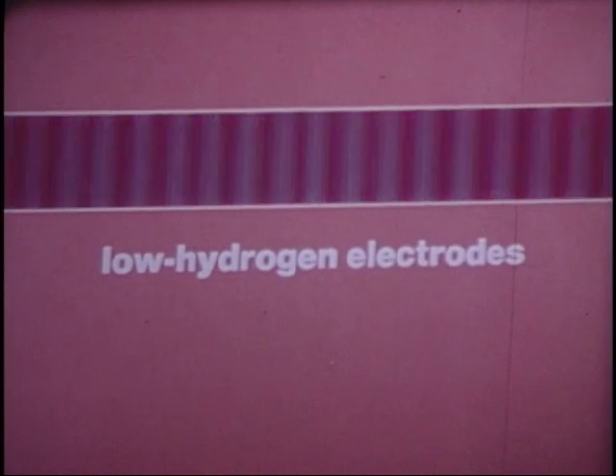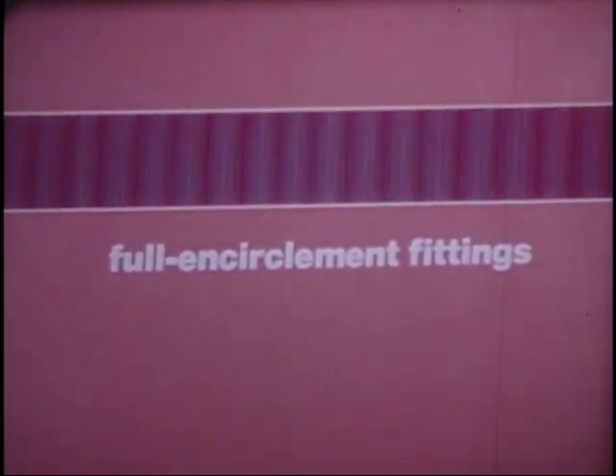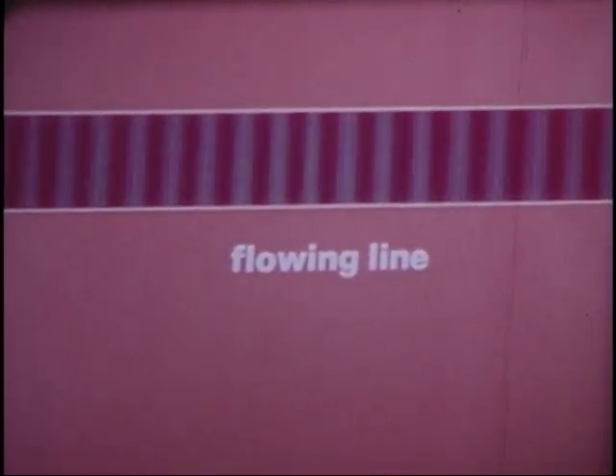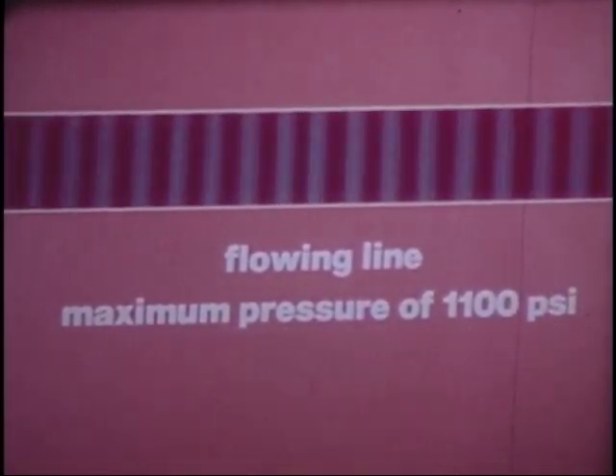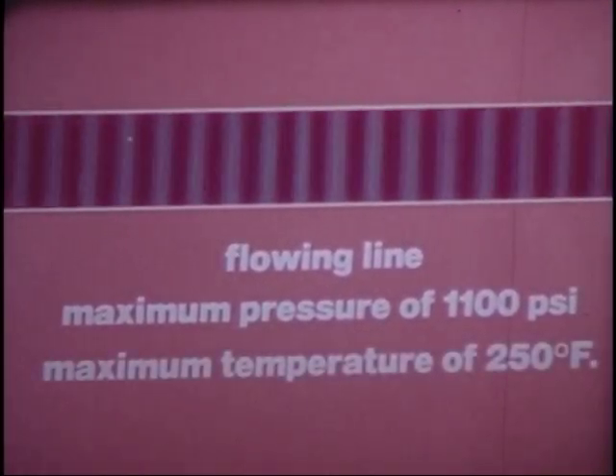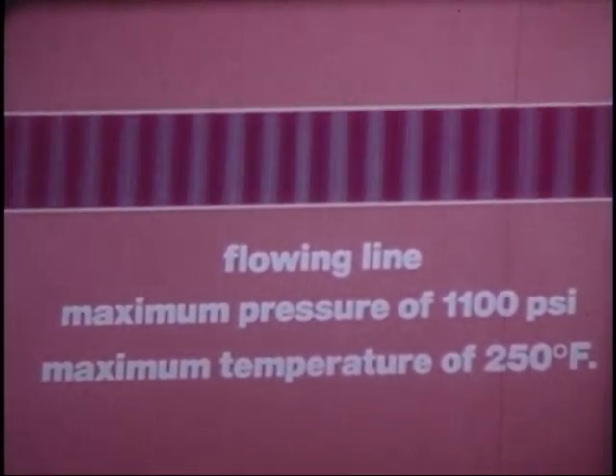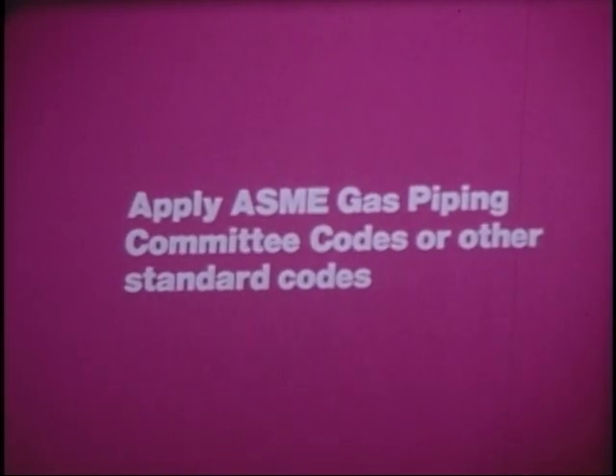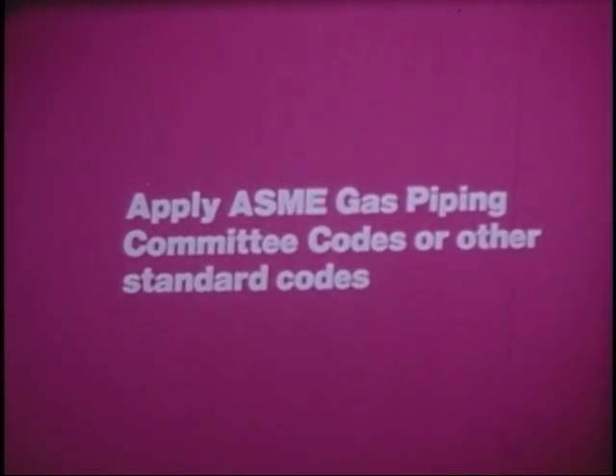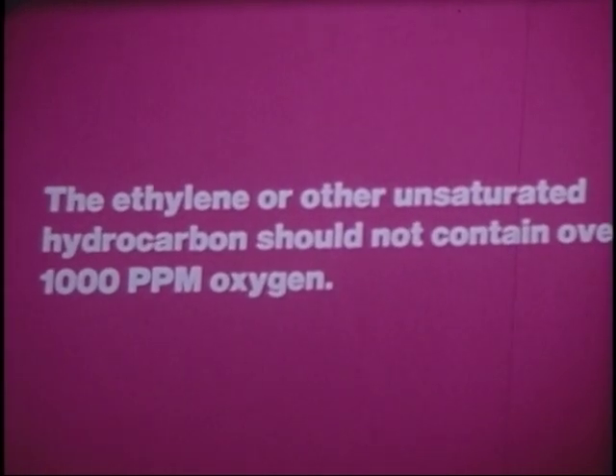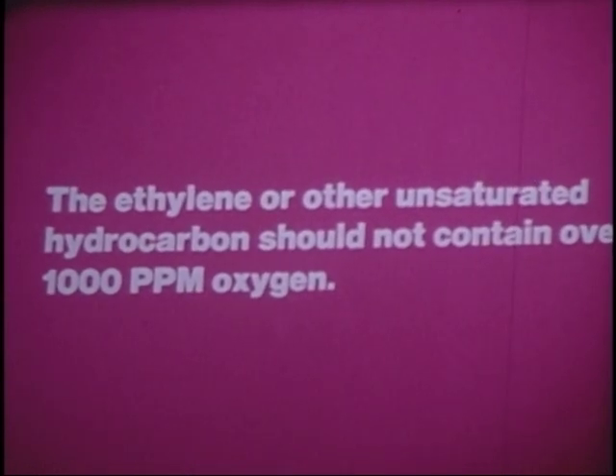When a line contains ethylene or other unsaturated hydrocarbons, use low hydrogen electrodes. Use full encirclement fittings. Have a flowing line with a maximum pressure of 1100 psi or lower and a maximum temperature of 250 degrees Fahrenheit or lower. Apply ASME Gas Piping Committee codes or other standard codes. The ethylene or other unsaturated hydrocarbon should not contain over 1,000 parts per million oxygen.